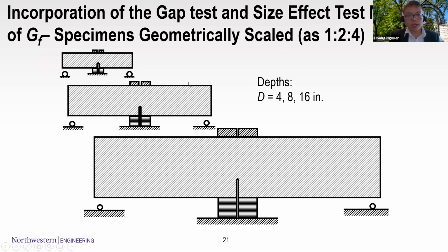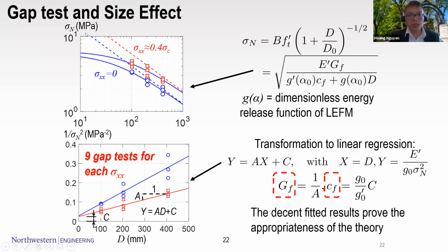All right, so now we incorporate the gap test and the size effect test method to get the fracture energy and to see how the crack-parallel stress affects the fracture energy here. You can see that we scale the entire setup, and we keep the aspect ratio the same, and also the out-of-plane thickness the same. The result from the gap test can be shown here, and it follows quite reasonably with the size effect method. And from these, we can extract the G_F and the c_f, as I mentioned before.